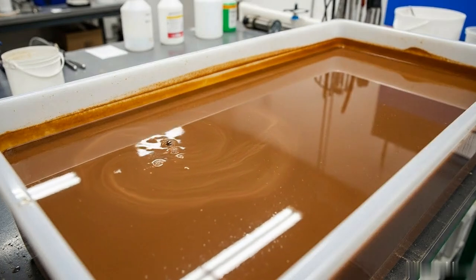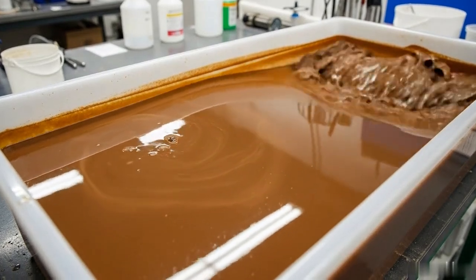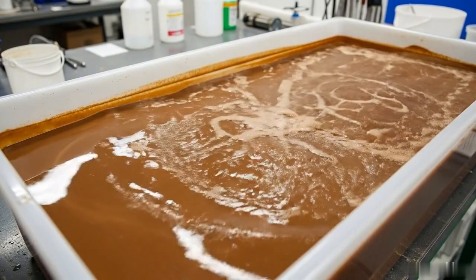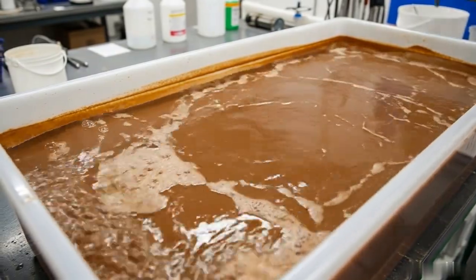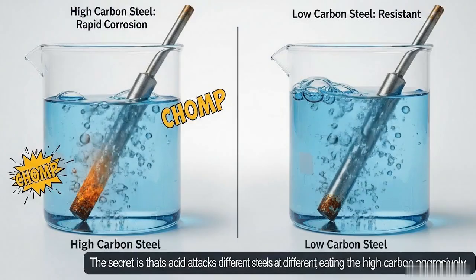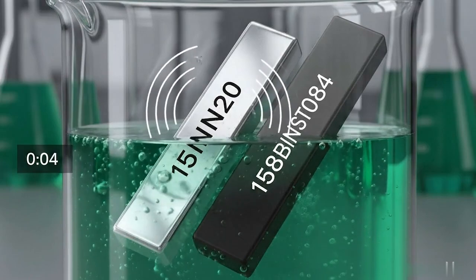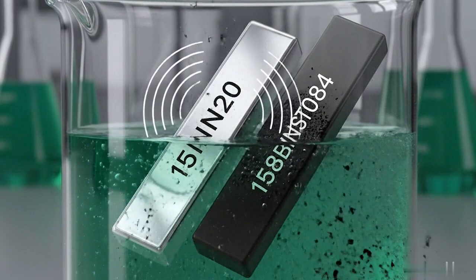This is the part that finally unveils the soul of the Damascus using a solution of ferric chloride. The secret is that this acid attacks different steels at different rates, eating the high carbon aggressively. The nickel-rich 15N20 resists the acid, staying bright while the 1084 darkens, creating our contrast.